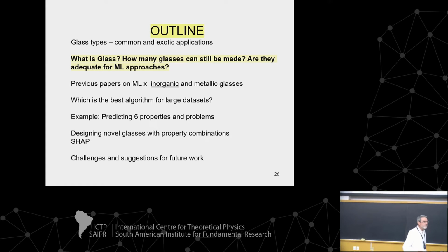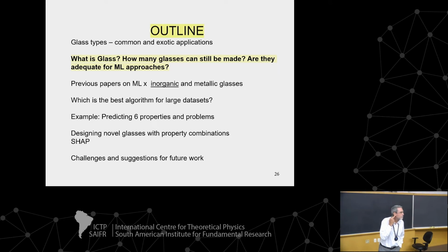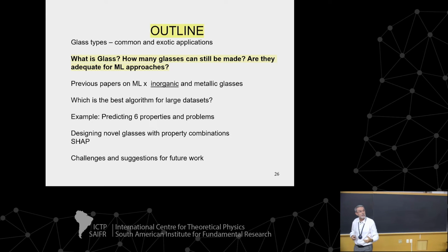So when you say that you can improve the ductility, does it mean that you can have a glass that can plastify before breaking? Well, it's not plastic in the sense that they're not as ductile as a metallic material. But there is a property called K1C, the critical stress intensity factor, which measures the area under the stress versus deformation curve. That area is a measure of the ductility. That area typically triplicates when you crystallize a glass. It does not come closer to a steel, for instance, but it increases the toughness of the glass. It becomes more ductile, as evaluated by the area under the stress-strain curve.